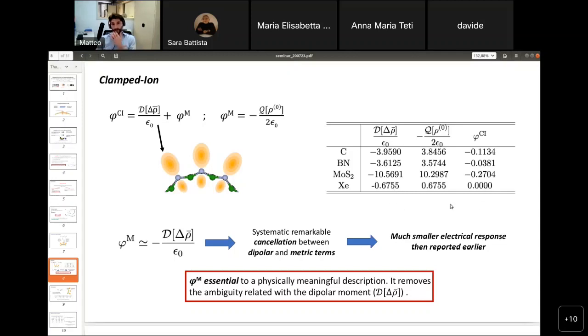In order to better explain why the metric term is so important, let me refer to the last row of the table. This is a calculation performed on a hexagonal lattice of xenon atoms, where the xenon atoms are spaced enough to be considered non-interacting. So basically, we are just considering a layer constituted of neutral spheres, and if you think about bending it, clearly the expected response should be zero. I have a two-dimensional layer of neutral spheres, I bend it however I want, and I still remain in the region where the atoms don't interact, so I shouldn't see any physical response.